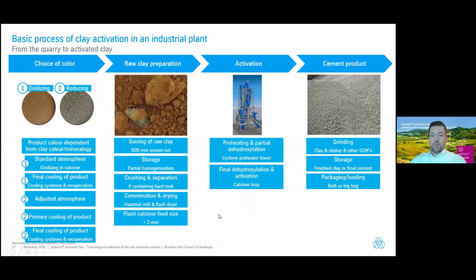Good. Now let's go a bit deeper into the process. So what are the typical steps? I mentioned several times that the color is of very high importance here. So depending on the clay you have, meaning depending on the iron oxide contents of the clay, it will become a reddish color after activation. And in most markets, it is not wanted from the end customer. The end customer would like to have a gray product. And this is what we can do.